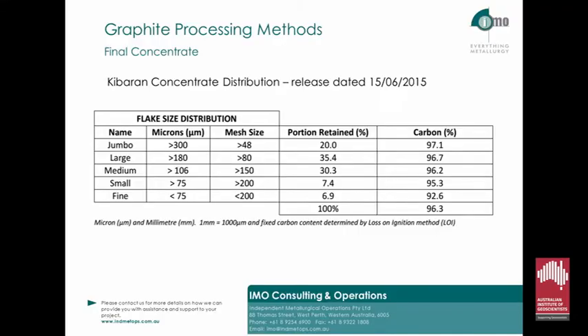Once the final concentrate is produced, it's then typically sized to determine the flake distribution, and then each individual size fraction is assayed to determine the graphite content. I've shown an example from a Kibaran release from 15th of June 2015 as an example of the final flotation concentrate. I must stress that this result was achieved after a significant amount of test work trialling different flow sheets and conditions, and that the flow sheet I showed previously is not the final flow sheet selected for Kibaran.